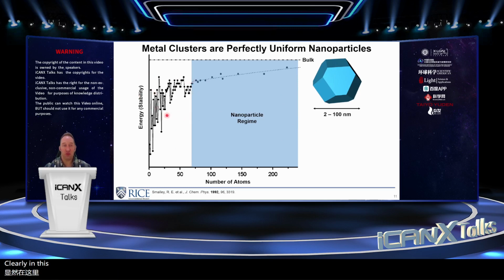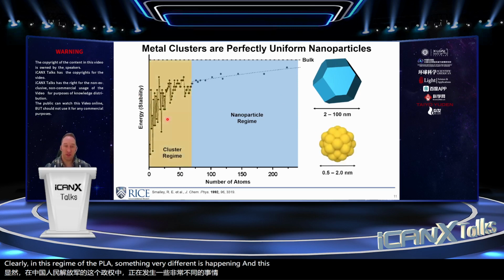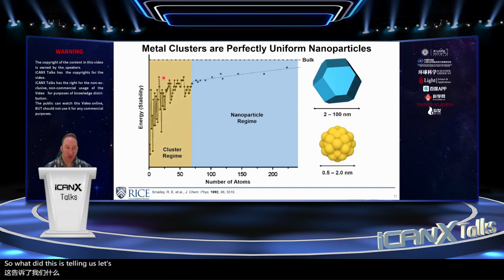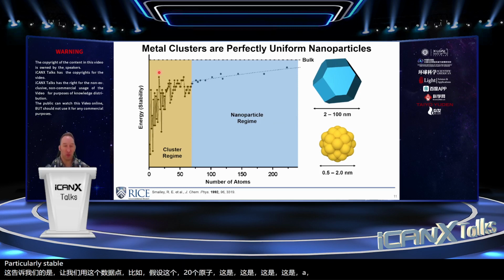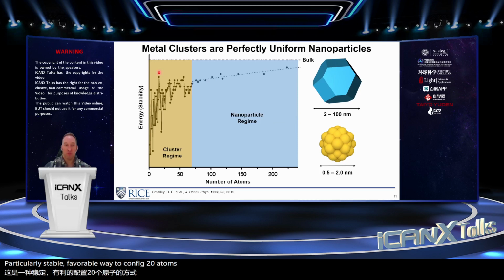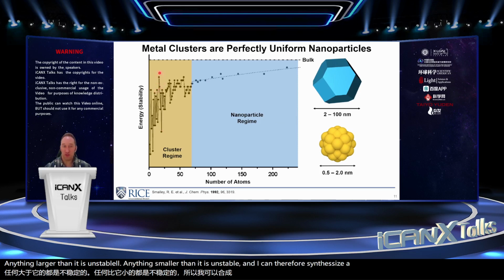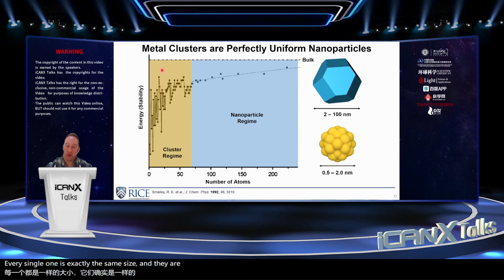Clearly, in this regime of the plot, something very different is happening, and this is the cluster regime. So what this is telling us, let's take this data point, for example, let's say that's 20 atoms. This is saying that there is a particularly stable or favorable way to configure 20 atoms, but if I add one atom, or if I subtract an atom, there is no good way to configure 21 or 19 atoms. And so what this means is that if I target a synthesis for objects of exactly this size, anything larger than it is unstable, anything smaller than it is unstable, and I can therefore synthesize a solution of nanoparticles that are perfect. Every single one is exactly the same size, and they are therefore molecules. So this is a regime of nanoparticle molecules.